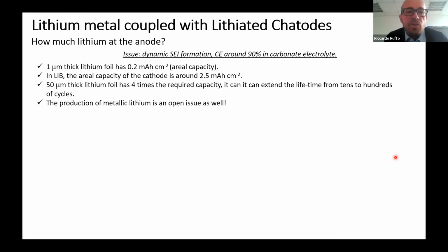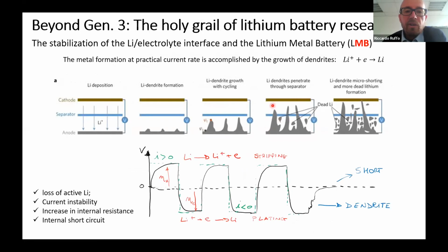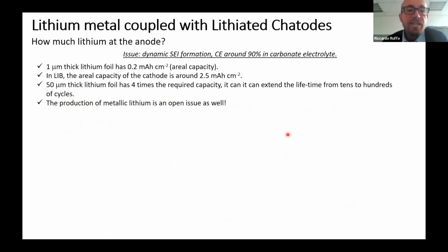So the main issue here is the dynamic formation of this SEI, the passivation layer, which should cover all my lithium, and during the lithium stripping and plating it is consumed as well. So we call this a dynamic SEI formation, where the Coulomb efficiency cycle by cycle is 90% versus the 99.9% that we have in lithium-ion batteries.